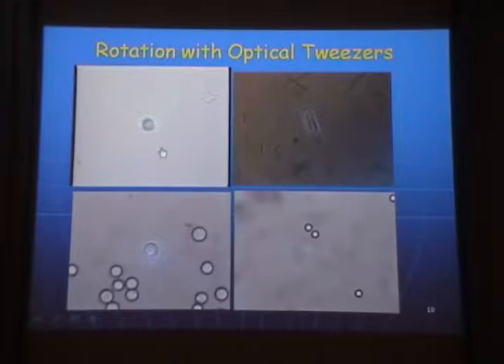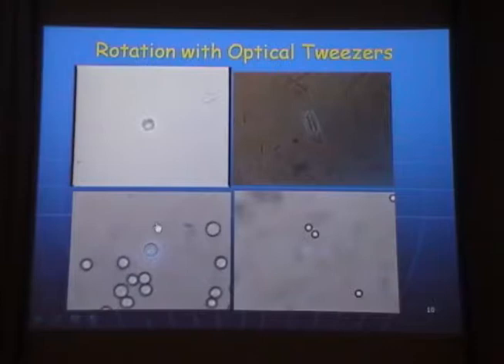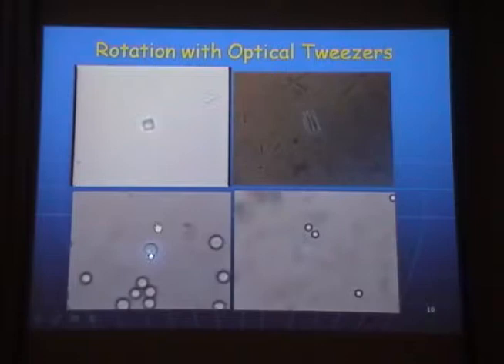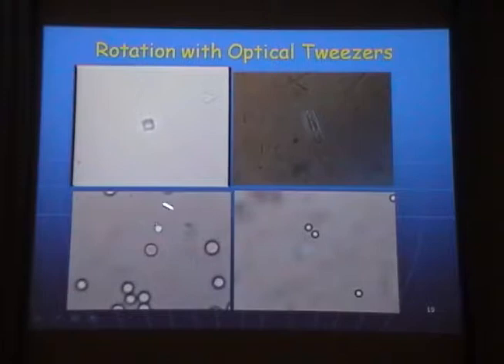So this is a calcite crystal produced in-house, and it rotates quite slowly, but it does rotate. So what we are doing here, we have circularly polarized light, and we trap the particle, and as it is trapped, it also starts rotating because we have transfer of spin angular momentum. Then we have perfectly spherical particles, which I will tell you more about, and we trap it and it rotates rather fast. Now this particle will start moving around, but because it is so round it's difficult to see its rotation, and only by looking at the liquid rotating around it will we recognize the rotation, and I will talk more about those. We can have elongated particles which we put into linearly polarized light, and we'll get rotation occurring there too, and we'll touch upon that.